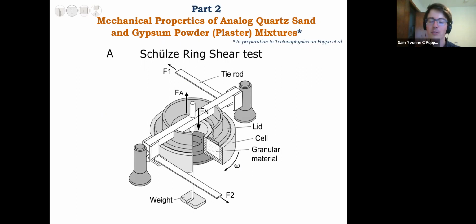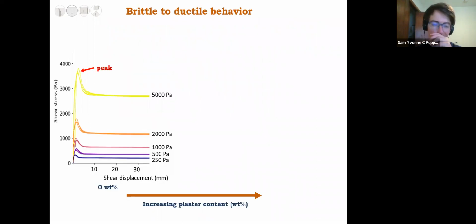But what we did, first of all, is run ring shear tests. In a ring shear test, you deposit the material in an annular cell. You place a lid on the top, load the lid, and then rotate the sample. And the lid itself is connected to stress sensors, which allow you to measure the shear stress during that rotation. And so get an idea of the mechanical behavior, the strain behavior of the material. And for pure sand, the shear stress curves, shear strength curves are quite known. You see here an example for pure sand.